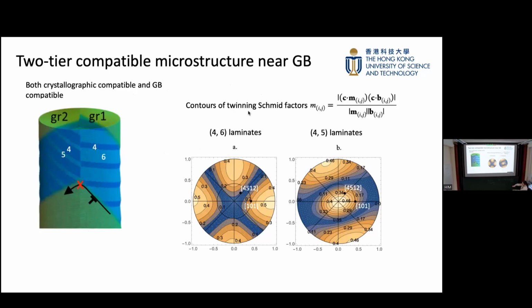Okay, so if we load it, there is still the resolved shear from this side and the resolved shear from that side. So here we look at the spatial orientation distribution of the shear for the twin laminates for 6 and for the twin laminates for 5 in their own orientation space, and we plot that. So we plot the orientation here, and we find, okay, for the 6 twin laminate here, if this is 4, 5, 12, which is actually GR2, it corresponds to a lower Schmid factor.